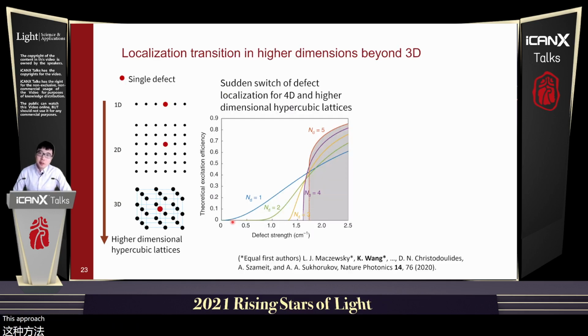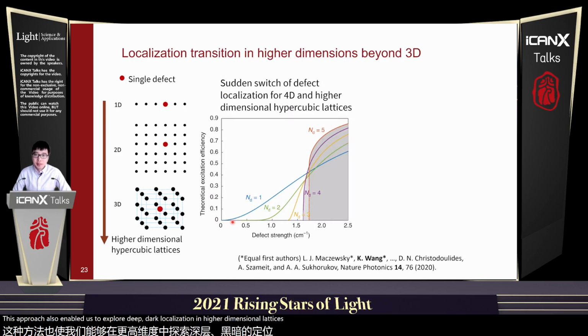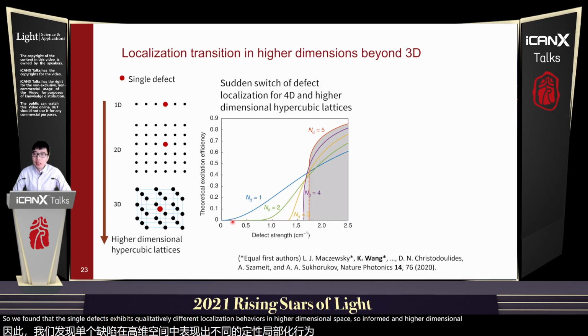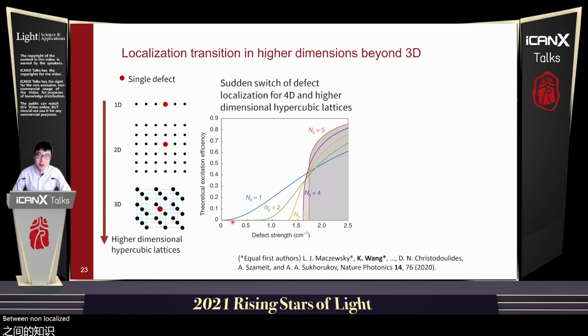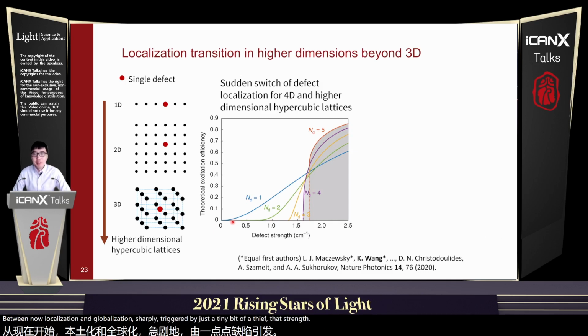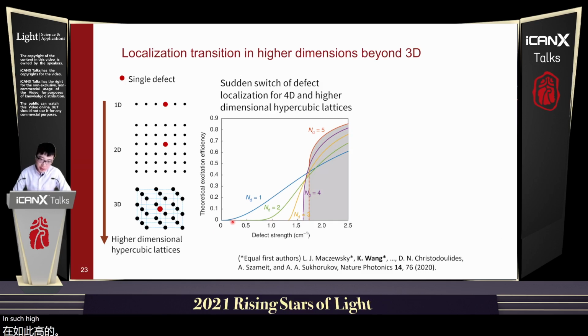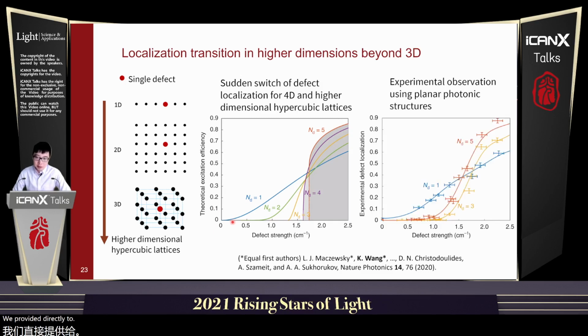This approach also enabled us to explore defect localization in higher dimensional lattices. So we found that the single defect exhibits qualitatively different localization behaviors in higher dimensional space. So in 4D and higher dimensional hypercubic lattices, there is a thresholded switching between non-localization and localization, sharply triggered by just a tiny bit of defect strength variation. And such high responsivity may be used for advanced sensing applications. We provided direct experimental evidence of such a prediction using the transformation we developed.